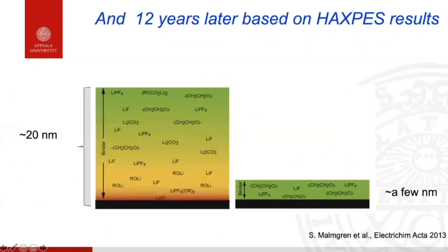And then 12 years later, we used new methods. So you can really use what's called HAXPES. It's a hard X-ray photoelectron spectroscopy. It's a kind of XPS technique where you can tune your photon energy so you can go deeper and deeper in. And there we could more or less confirm that the lithium fluoride crystals, you could see them all through this mushy layer of organics, though you had more of salt reduction products close to the surface and more of the mushy organic on top of the SEI.